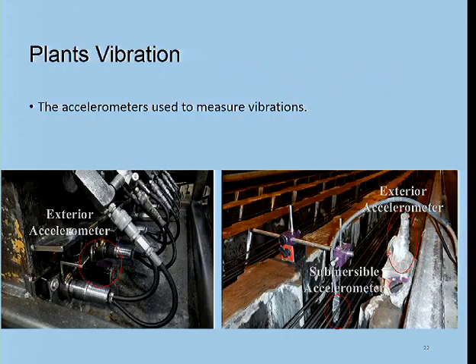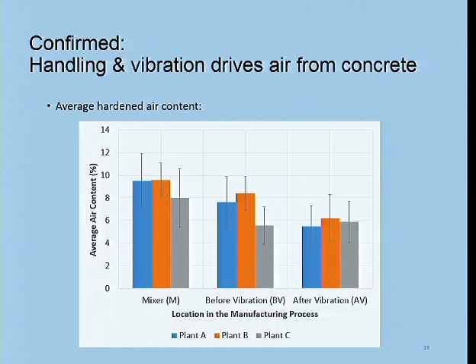You can see here a little more how we attach our accelerometer to the equipment, so we get a sense of the difference of the acceleration being felt by the material versus being felt by the forms themselves. One thing that was important here is that we confirmed that the handling and vibration of concrete drives air from the concrete in all these different plants. So we have plant A is the blue, plant B is the orange, plant C is the gray, and in all of these cases, from the left to the right, at the mixer, before vibration, after vibration, you see this tendency to lose air at these different steps of the process.